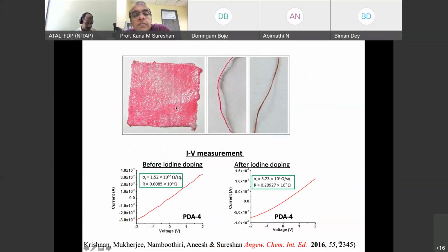This is the real data. Actually, this is the conducting polymer, conducting cloth we have made. You can see the PDA color. And this is one individual fiber, this is without doping. You can see the surface resistivity is 10 to the power 8 ohm per square. That is sufficient. That means it is a semiconductor. That is sufficient enough to dissipate the static charge. You can also reduce further by doping iodine. So that also we have shown in collaboration with a physics colleague here.